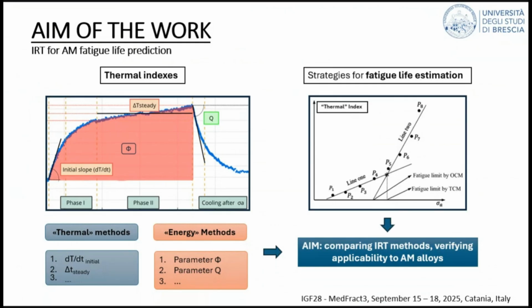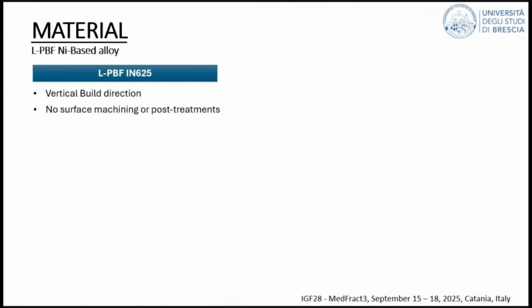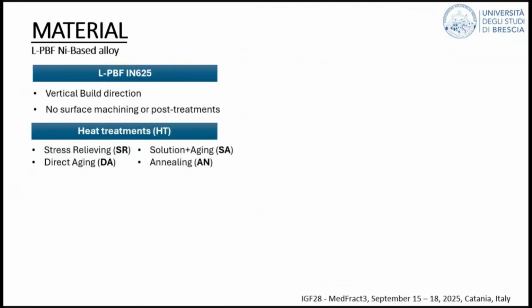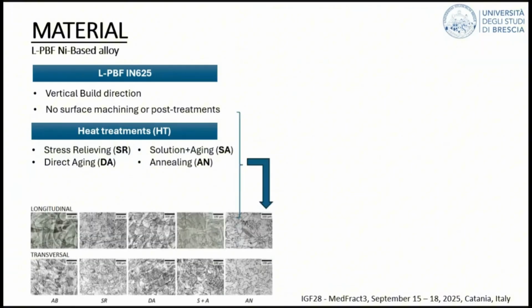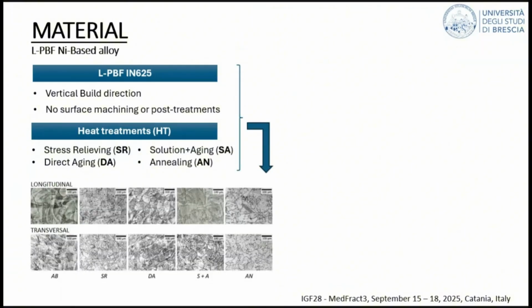And as I said, we applied a case study. We had some samples from a nickel-based alloy, laser powder bed fusion Inconel 625. This material was available under 4 different heat treatment conditions. This was part of a previous investigation.